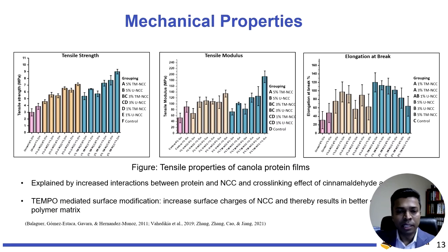When we look at the mechanical properties, one thing that you would observe is if you look at the canola protein alone, which you can see in here, the tensile strength of the canola protein-based films is around 3 megapascal. But when we add the nanocellulose without any modification, we can actually increase it up to almost 7 megapascal, which is more than doubling the strength of the material by adding 5% nanocellulose on protein weight. So this is a small amount of nanocellulose we're adding, but the material strength increases more than double.